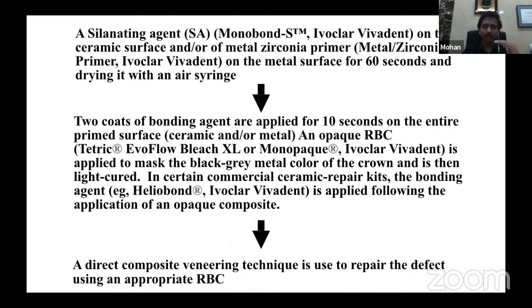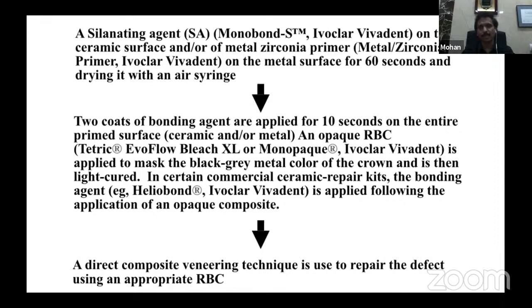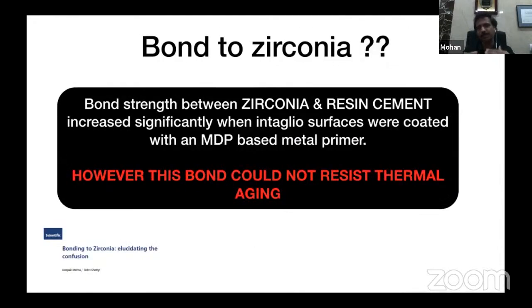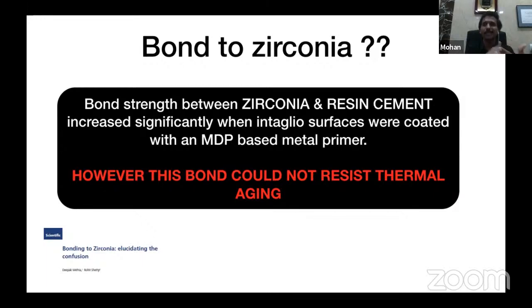Then once the surface treatment is over, what we apply is the Monobond. Monobond is a coupling agent which could be applied for metal ceramics, metals, zirconia, and the glass ceramics. Then we apply a bonding agent layer, polymerize it, and then proceed with the composite placement. So that is with regard to any of the surface treatment. So first is understanding the failure, then making the decision to repair or replace, then doing the surface treatment, and then doing the adhesive or the coupling agent.